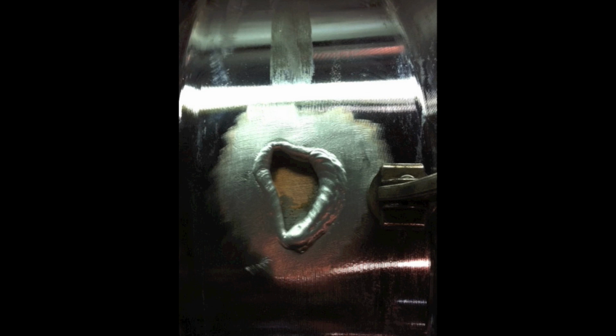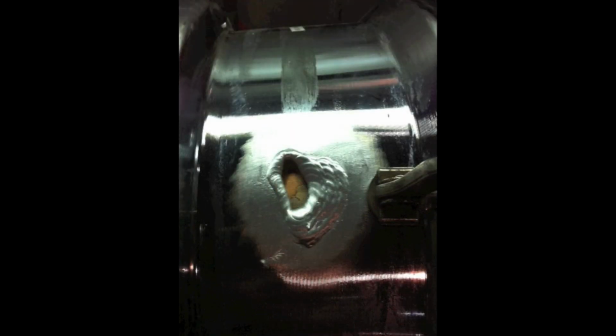Now you don't want to just continuously weld this thing. You want to let it cool for a minute or two between beads, but gradually, bead after bead, you can close a weld like this and fill up a hole. And this guy did an awesome job on this thing. And with that copper on the back side, it lets the metal sink through just a little bit because it's not actually touching. And then all he had to do was a little touch up on the back, and now he's got a good weld repair, and it's going to hold air again.